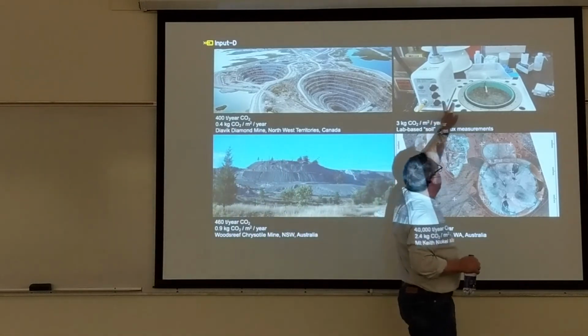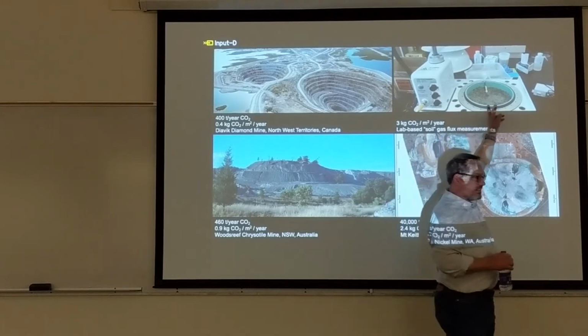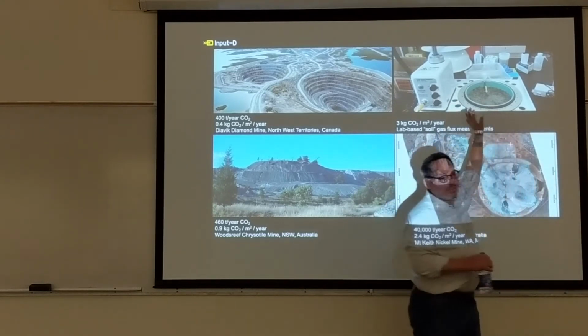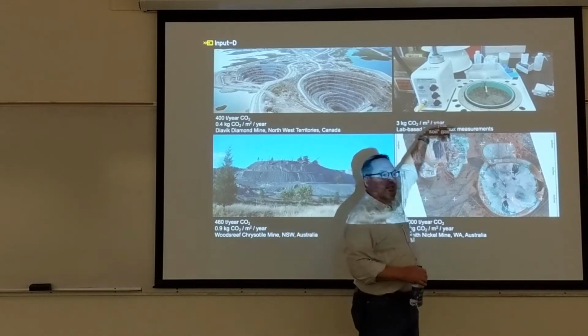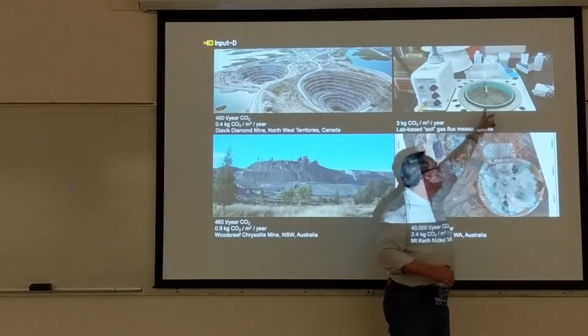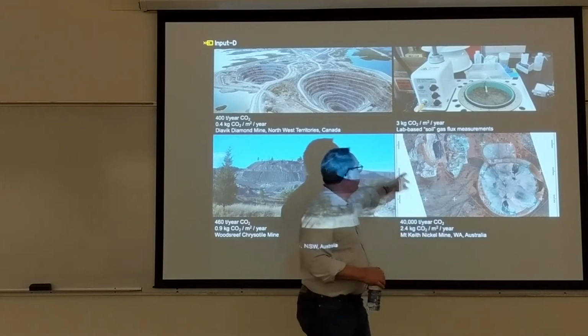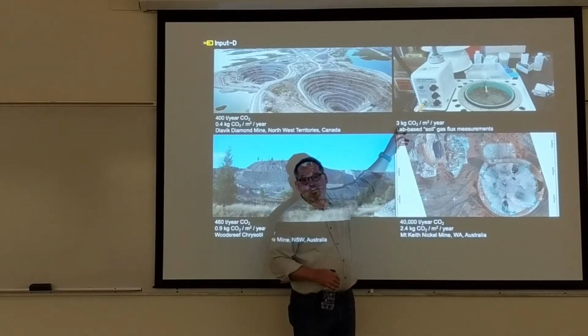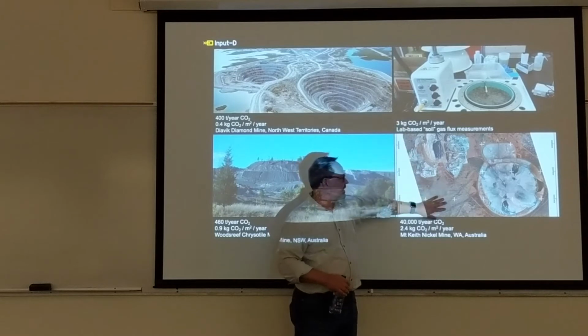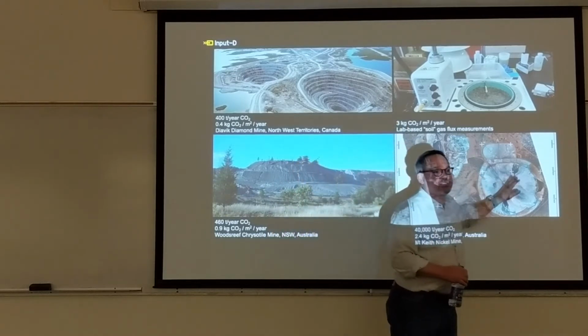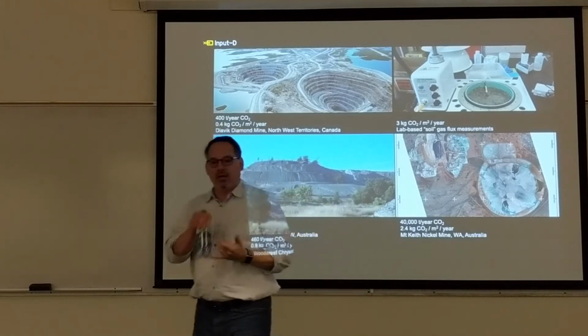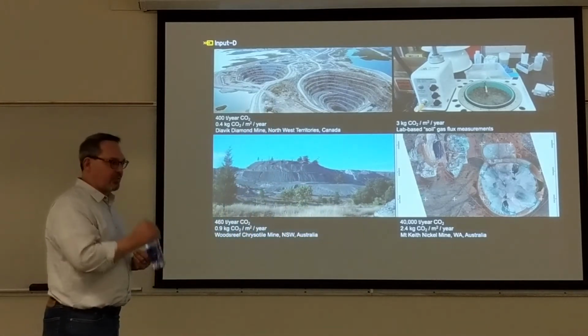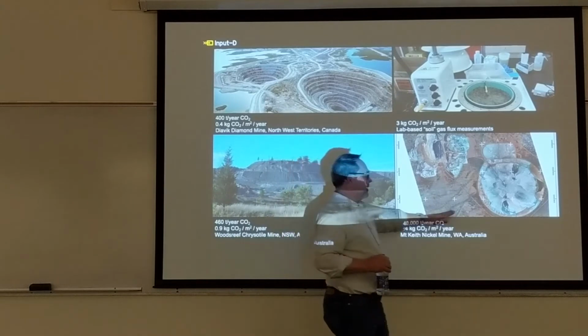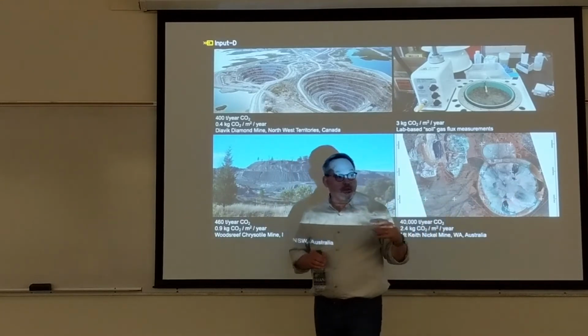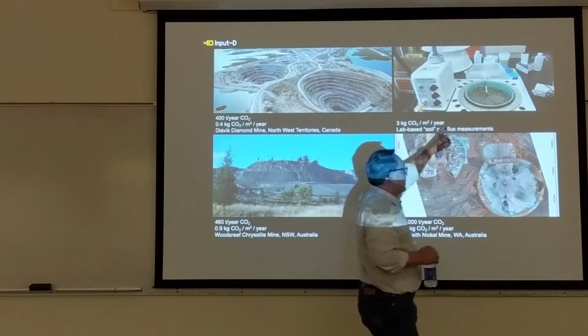Interestingly, if we take a proper soil gas flux measuring system, instead of $100, this costs $40,000. If we use a system like this, we can measure the CO2 drawdown of nickel tailings in our laboratory environment, and we get 3 kilograms of CO2 per meter squared per year. So we get virtually identical drawdown rates. This is based on 3 years of a PhD study measuring the abundance of carbonate minerals on 8-year-old surfaces, 7-year-old surfaces, 5-year-old surfaces, 4-year-old surfaces, basically getting a rate of carbonation from mineral abundance data versus measuring simply changes in concentration of the CO2 in the space.